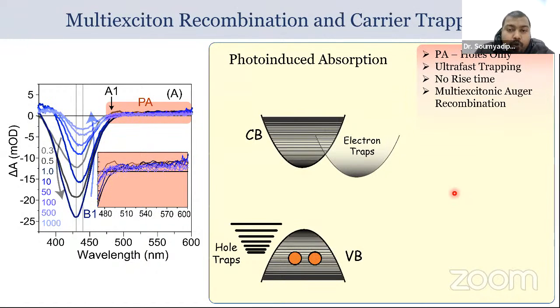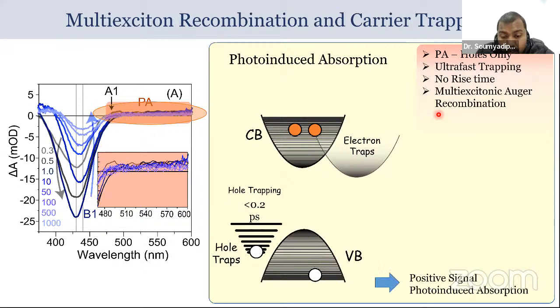Now, the last part. As you can see, in this part there's a very low amount of positive signal, but still the signal is there. And that is known as photoinduced absorption. When you are talking about photoinduced absorption, you are talking about holes only. What happens? If you excite the electrons, they go up, and at the same time, the hole can be trapped as well. The hole can be trapped, and this occurs in less than 200 femtoseconds. And then the hole in the trap and the vibration level goes to the higher energy level.